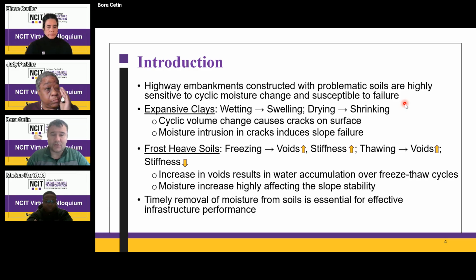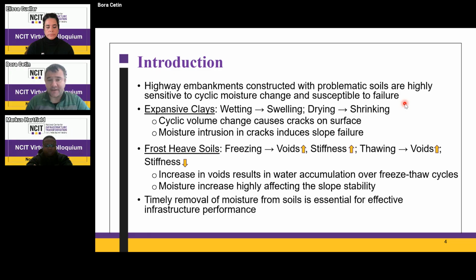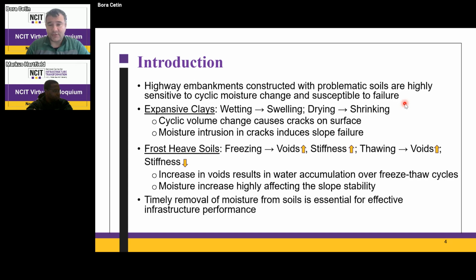Similar problems occur with frost susceptible soils. When you have the presence of moisture and the weather starts freezing, the volume of the ice is higher than the volume of the water. It expands, puts a lot of pressure and distress on the roadway systems from the embankment, and it causes longitudinal cracks and fatigue cracking. When it thaws, that's actually when we get the majority of the damage, with thaw settlement. We call this freeze-thaw strength loosening. The bearing capacity of the highway embankments is lost, and this loss can be very significant. The embankment soil is very wet, so there are spring load restrictions.